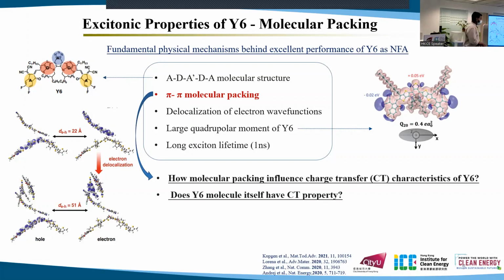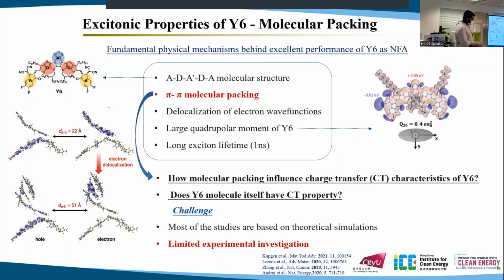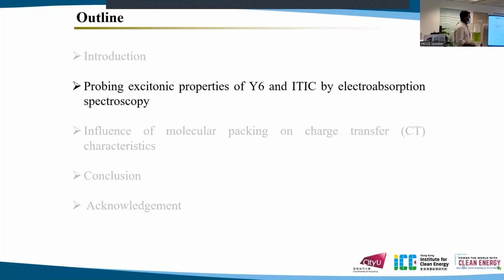That's why we were curious to know how this molecular packing influences the CT characteristics of Y6, or does the Y6 molecule itself have CT property? But the main challenge was that most of these studies were based on theoretical simulations like DFT or molecular dynamics simulations, with limited experimental investigation. That's why we wanted to probe the excitonic properties of Y6 and ITIC by means of electro-absorption